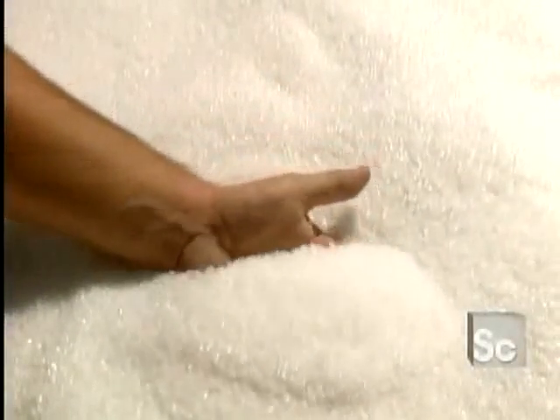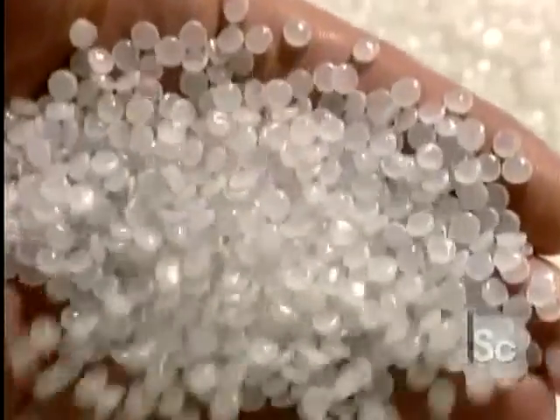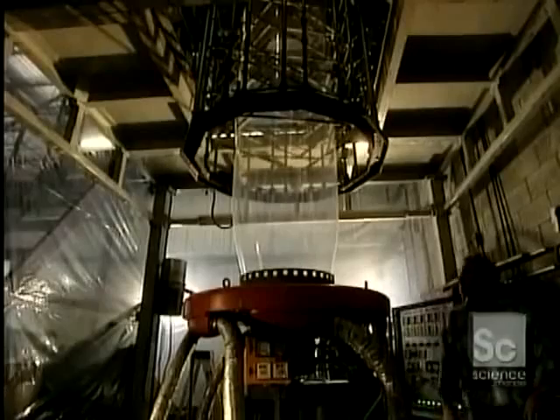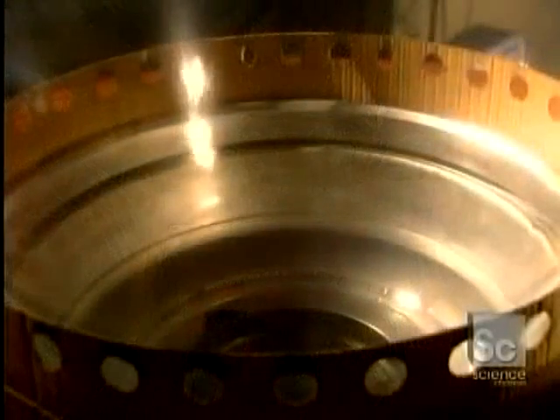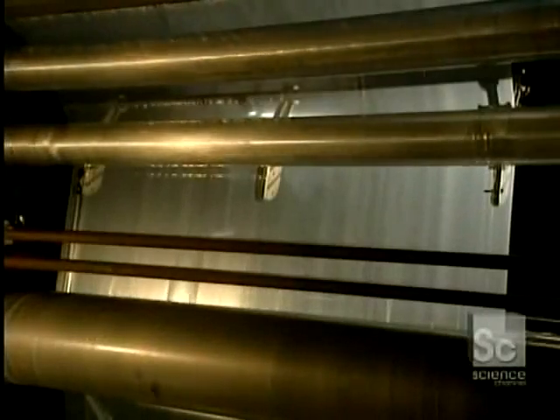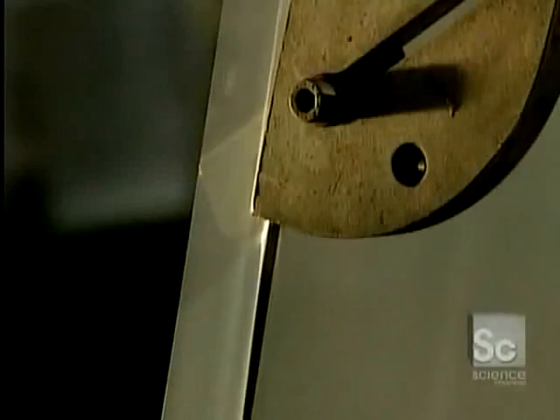Plastic bag manufacturers often start their production cycle using these granules. The beads are heated to a molten state and mixed to a homogeneous melt. A process called blow extrusion blows a film of molten high-density polyethylene upward into a tube shape. This tube cools as it ascends the factory, often rising 2 or 3 stories before being fed into a system of rollers that stretch, fold, and cut the material into the desired rectangular geometries.